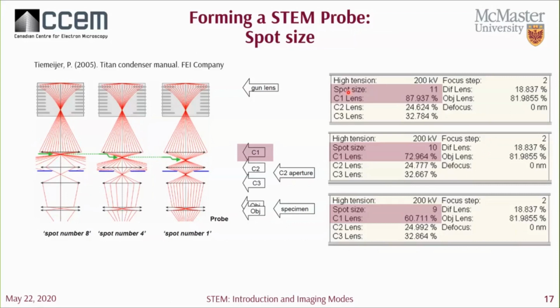As you can see here, this is just an example from the microscope. We have a spot size of 11, 10, and 9. And as you can see, as we increase the spot size, we're increasing the strength of our C1 lens. Normally, increasing the spot size by 1 tends to decrease the beam current by half. So ergo, in using a higher spot size to form a better probe, this gives us a more dim beam, or a less bright beam. So it's probably good that you have a fixed source to increase the brightness of your probe, allowing you to get a good signal on your detector.